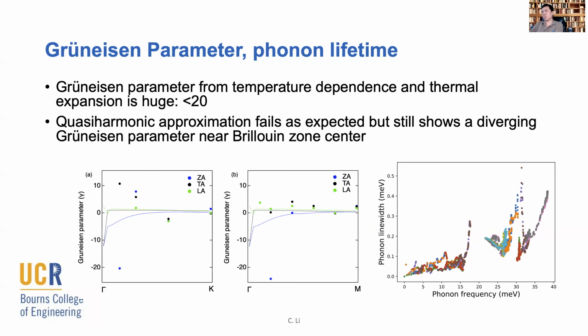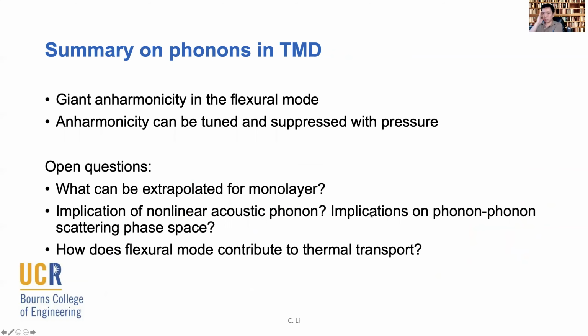So what we are trying to see here is how much this flexure mode could contribute in terms of thermal transport. There are a few ways it can do so, because this type of phonon can both enhance or suppress phonon transport. Because at low temperatures, usually you do need a certain sizable phonon population in order to carry enough heat. And lower energy phonons help with that. And those lower energy acoustic phonons of the flexure mode can be easily populated even with relatively low thermal excitation. So that may allow the system to transport more heat at low temperature.